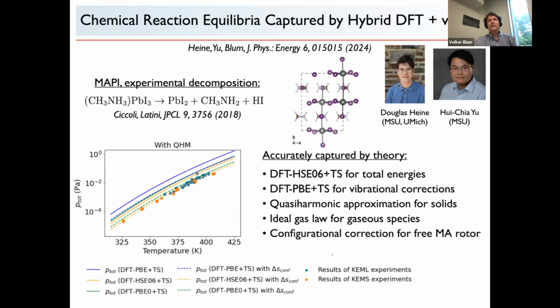We did a benchmark study of methylammonium lead iodide, this decomposition reaction here, because there's experimental reference data for this decomposition of the material into lead iodide, methylamine, and hydrogen iodide that measures the vapor pressure of a crystal in vacuum, essentially. And the experimental data are the points here. And to cut to the chase, we can do a computation using hybrid functionals, which are dispersion corrected, for total energies, then do a vibrational correction using a generalized gradient approximation, PBE, to get free energies out.